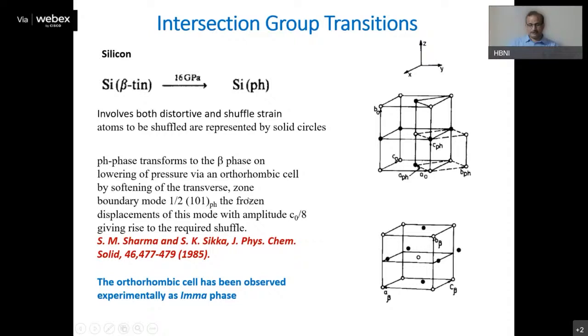Generally, this intermediate phase may not be evident when the phase transition happens, if the phase transition is very rapid. But if it involves some barrier, then there is a possibility that this intermediate phase can even be seen in experiments. In fact, if you see the phase diagram of silicon, people show some intermediate phase between the beta-tin and primitive hexagonal phases, and that is the Imma phase. So this is the intermediate phase between these two phases.